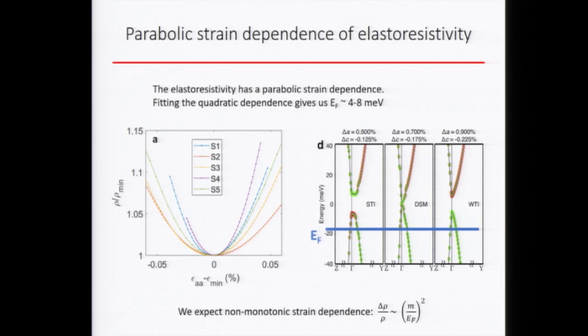How about the coefficient for this quadratic dependence? Do you think that's also intrinsic? Yeah, exactly. It actually directly tells you what your Fermi energy is, because this delta rho over rho is a dimensionless quantity, so it should depend on the gap quadratically, but the gap should be normalized by another energy scale, and the only energy scale here is the Fermi energy. This makes sense: the smaller the Fermi energy, the larger the response you should get. Can you check that by looking at the quantum limit? For this set of samples, we don't see quantum oscillation, so we cannot directly check that. We can check with the Hall coefficient, and that matches.